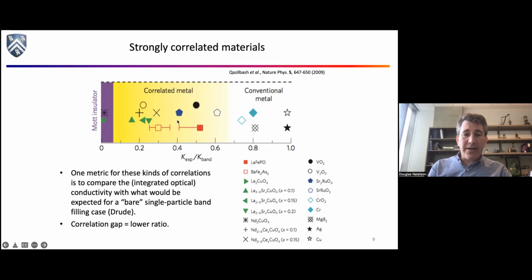But if you start talking about some of these systems where a simple naive calculation tells you they should be a metal, like this lanthanum copper oxide, and instead, you find it's an insulator. So that ratio becomes basically 0. So that's really something very dramatic has happened, right? Somehow interactions have really broken the standard picture of metals there.